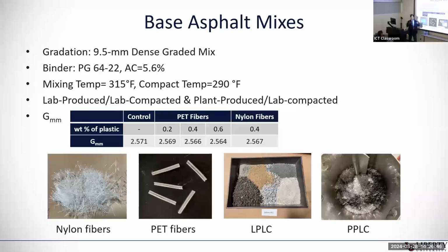So we have the two sets of the materials, and then we set up the 0.2, 0.4, 0.6% of the plastic, and then we run the GMM test. So this is the nylon fibers before we put this one into the mixture, and then the PET fiber shape, and then this is lab-produced, lab-compacted materials.